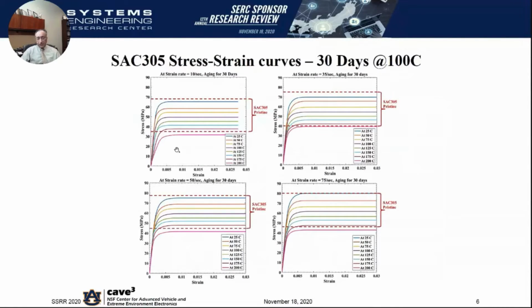So for each of the different strain rates, what we have done is we have measured a stress strain curve, and that's what a typical stress strain curve would look like. We are plotting the measured stress that's acquired from the force measurement of the load cell, and then we are measuring strain using both optical methods and mechanical methods such as LVDT, linear voltage displacement transducer, that's in our frame.